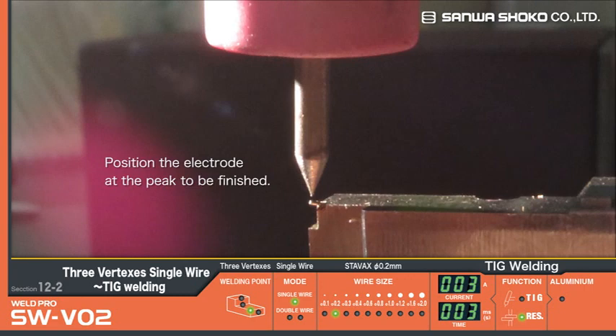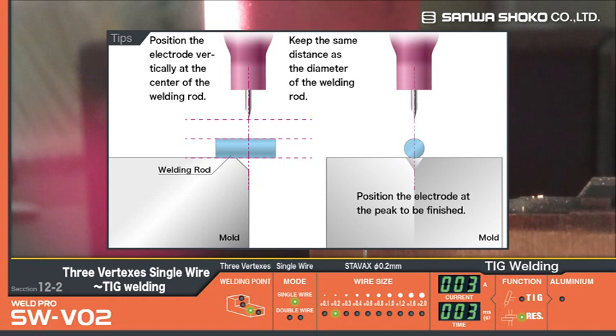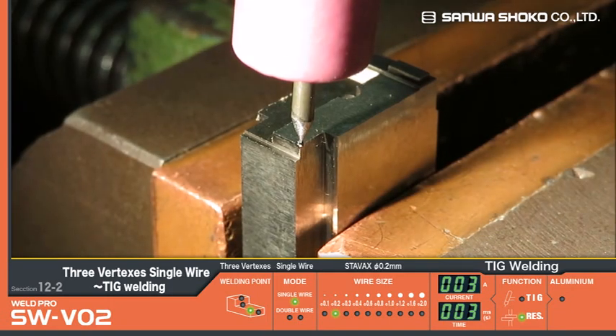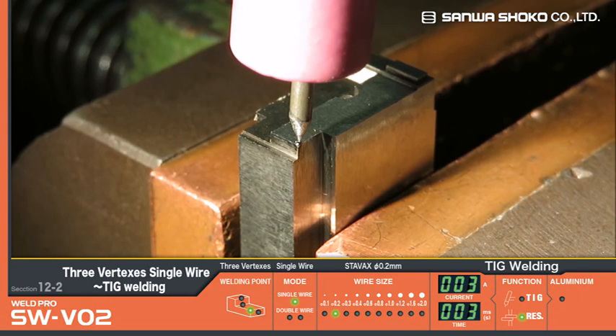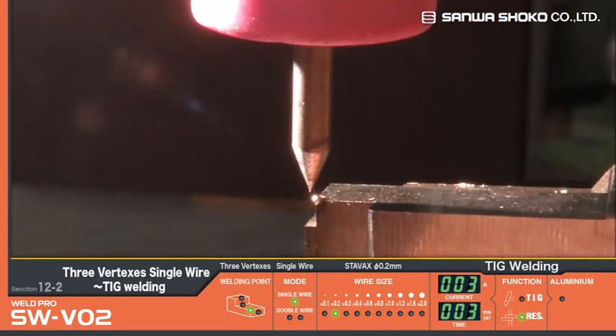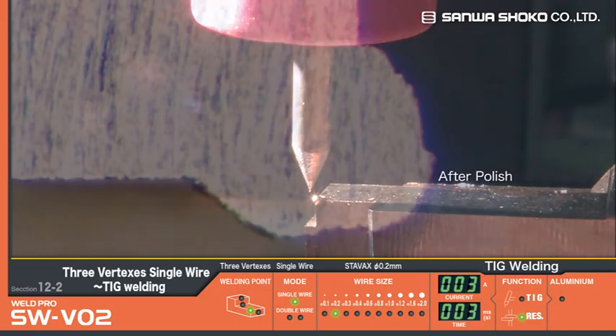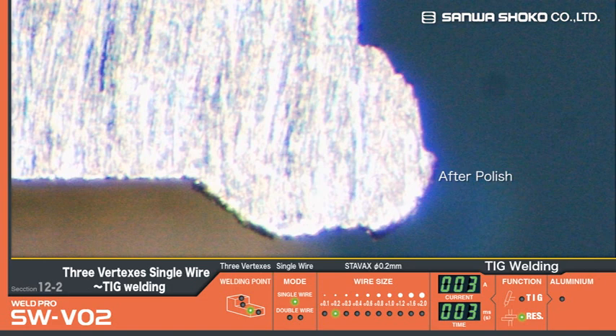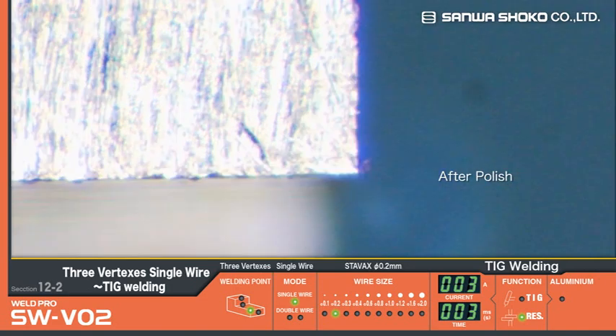Position the electrode at the peak to be finished. Keep the same distance as the diameter of the welding rod. In this case, the distance is 0.2 millimeters. Position the electrode vertically at the center of the welding rod. Even though the welded area is polished, it can be confirmed that no shrinkage is observed.